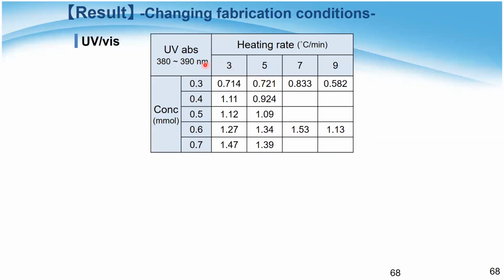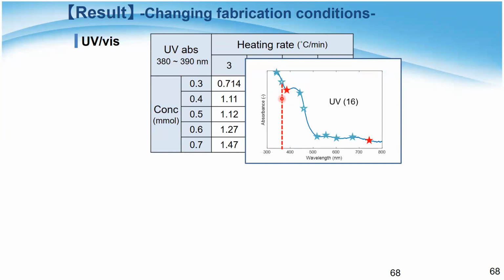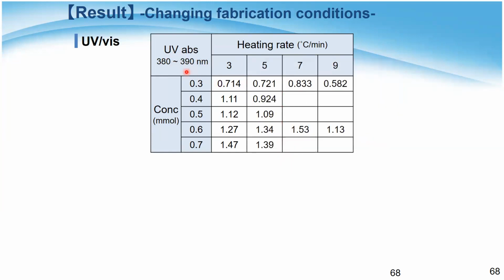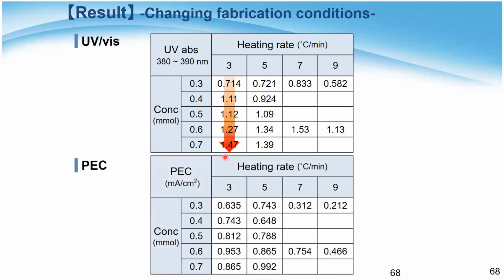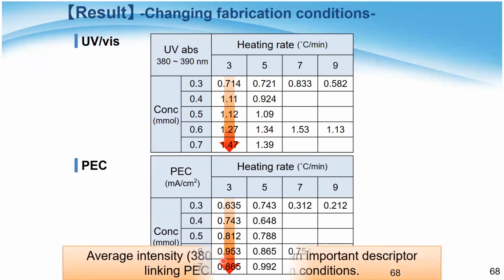So here's what we could find: this is a UV-Vis absorption around 400 nanometer. Again, this is not a band gap absorption, so this is an internal absorption band. By changing the heating rate and the concentration, this one was dependent on the precursor concentration. So as concentration increased, this UV-Vis absorption also increased. And then looking at the PEC performance, same as this trend, by increasing the concentration, PEC performance was improved. So this average intensity is an important descriptor linking the PEC performance and the fabrication conditions.